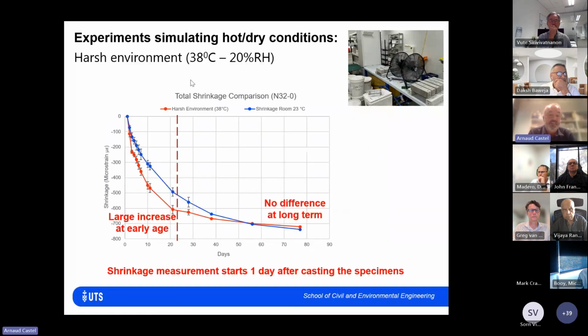So that's just one example of test results we had. That's still a 32 MPa concrete, no SCM, and in red is the total shrinkage at 38 degrees, and in blue is the total shrinkage at 23 degrees. We're measuring after 1 day, so it's total shrinkage, and we see a really important difference at early age between the blue and the red, and it was expected. And then after a while, there's not much difference. The two shrinkages are pretty similar.